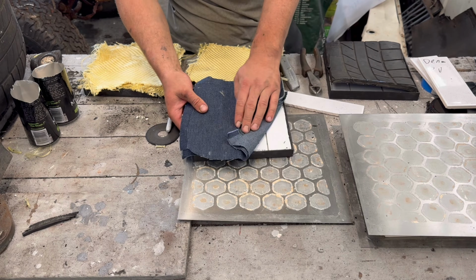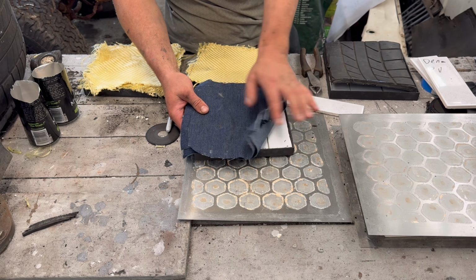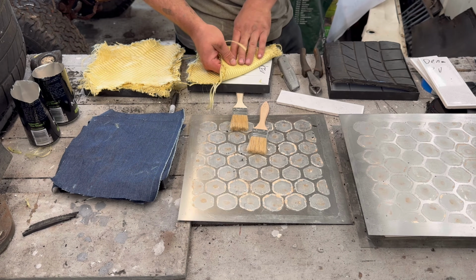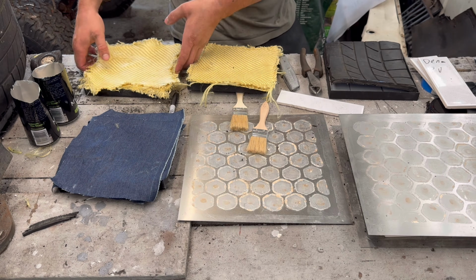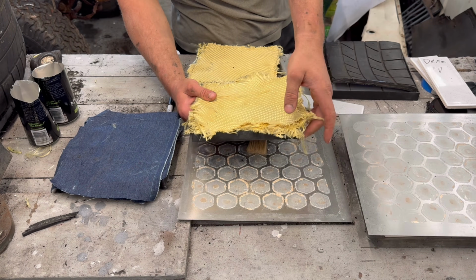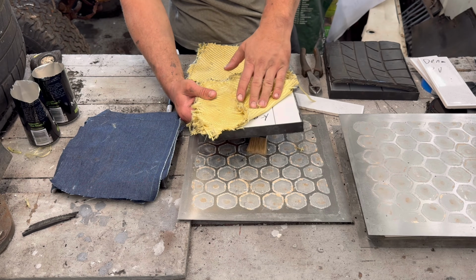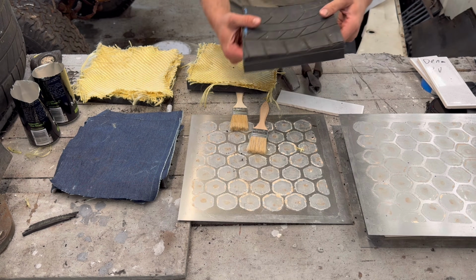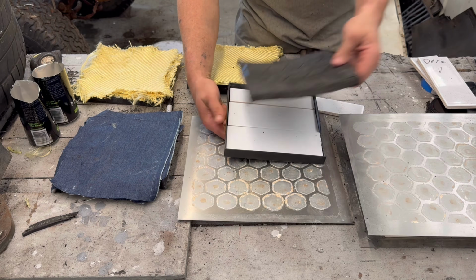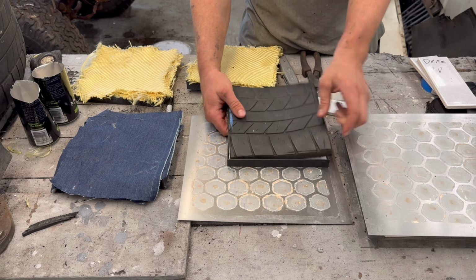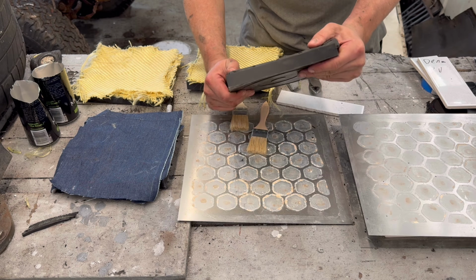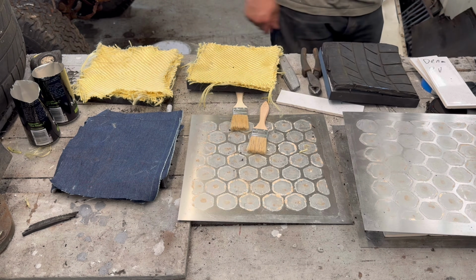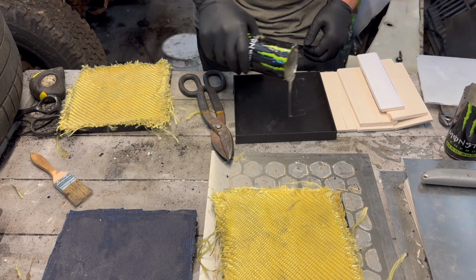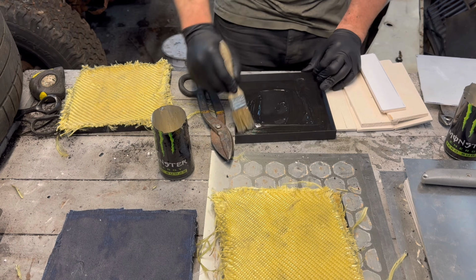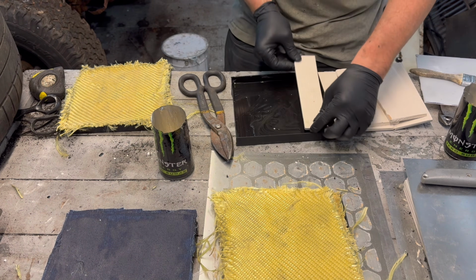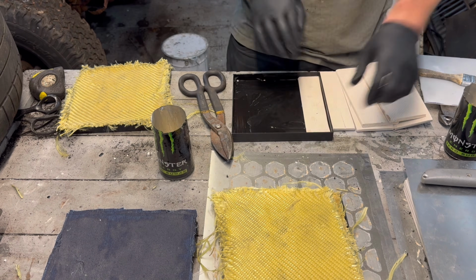To start with, we've got the denim and the Kevlar pieces, each with 2 layers of ceramic in each target, with around 6 layers of each material backing it. The denim and one of the Kevlars will have the softer polyurethane resin, and then the other Kevlar will have the epoxy. There's then also the tyre pieces, so we're going to have one with 1 layer of ceramic and a tyre. That's because the tyre is actually quite thick, so I wouldn't be able to use 2 layers of ceramic everywhere. And then there'll be one with 2 layers, and I think I'll put one of those metal plates into that as well. But for now, we'll build up one of these targets with 2 layers of ceramic and a 3mm plastic sheet of polypropylene at the back of it, all with the softer polyurethane resin.